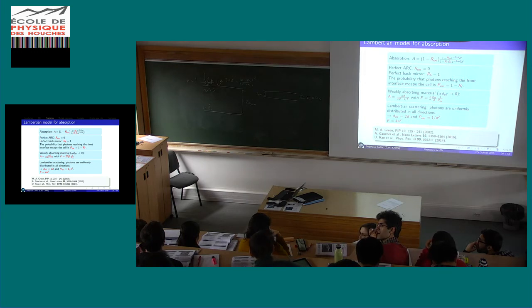That's worse than Lambertian, but it will be 4n² because you have very short light paths all going in and out, but the one light path that hits the scratch and gets reflected becomes more or less infinitely long and will give you the 4n² average, if alpha d goes to 0, in the very extreme limit.